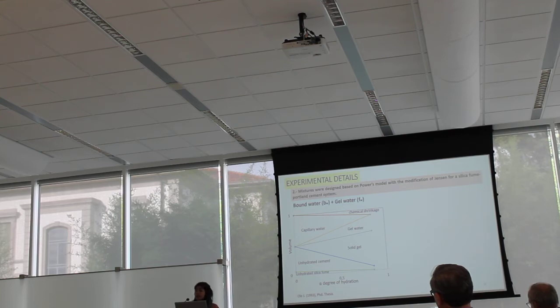But when you have silica fume, you have another system, because the silica fume is going to take water from the system. Powers says that the bound water was 0.23 grams per gram of cement, and the gel water was 0.19 grams per gram of cement.